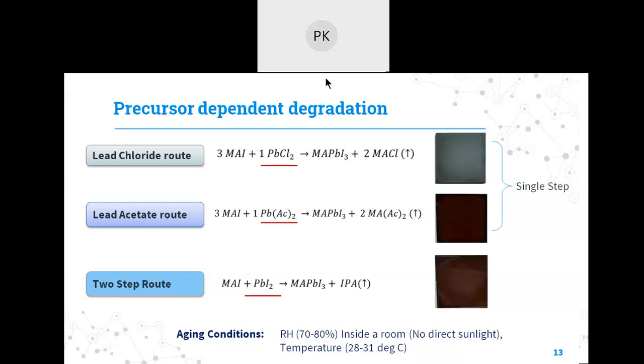So regarding the procedure, have you tried using tin? Yes, we have been trying replacing the lead with other elements, like using tin and bismuth, in our laboratory. But there are some problems with tin. First is the oxidation state of tin. Tin has two oxidation states, +2 and +4. What we use here is the +2 oxidation state for perovskite structure formation.